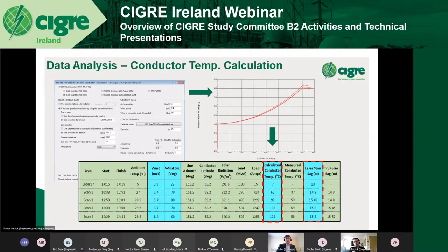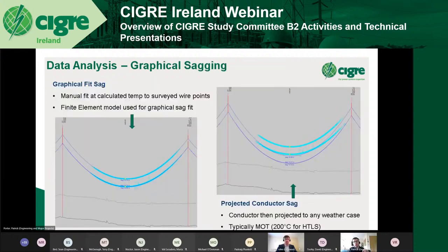What we said that we would do is repeat the exercise, i.e. calculate the conductor temperature and include that for comparison purposes, because ideally we should get the same results when we project it out to any temperature. But you'll note there the 2017 LiDAR, the top row, the ambient on the day was 5 degrees, calculated conductor temperature was 7 degrees, normal loading conditions on the line, so you couldn't get further away from what we had the day of the test, 30 degrees and 500 MVA. But we've included that as part of our comparison as well.